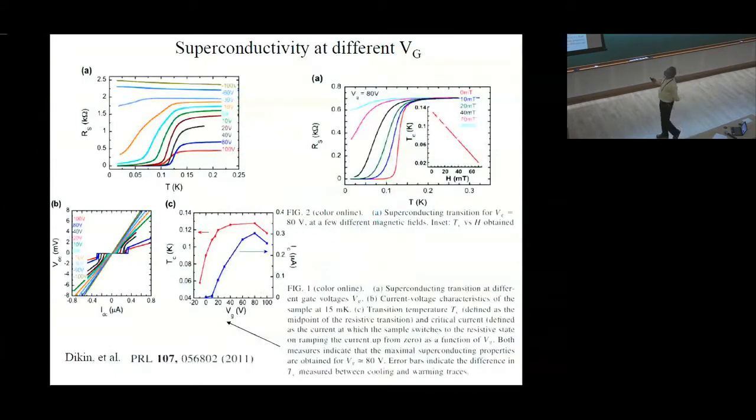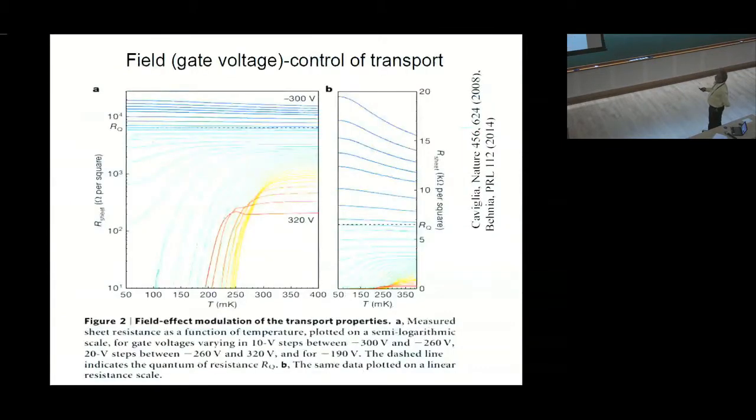So this is a study with respect to gate voltage, and one can show in the next one here, you can see that by changing gate voltage, you can actually go from the superconducting state to the insulating state. So there is a superconductor-insulator critical point here, where this number R sub Q is almost like h by 4e squared, which is like 2e bosons resistivity, almost close.